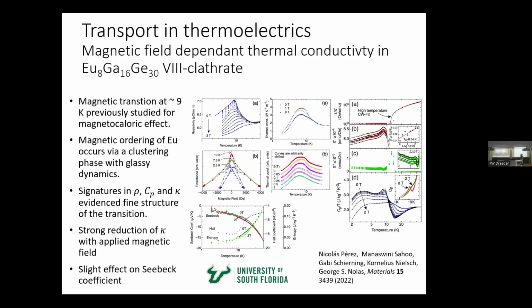So the reduction of thermal conductivity starts already here. The material doesn't need to be a long range ferromagnet; a short range ferromagnet already works. So what is the coupling? This shouldn't be an electronic thing, so it's not a reduction of thermal conductivity due to conduction of electrons, which exist in this material, because the trend goes the other way. The material becomes more conducting, so the thermal conductivity should go up for that reason. It does not, so it needs to be a structural lattice or phonon-related issue.